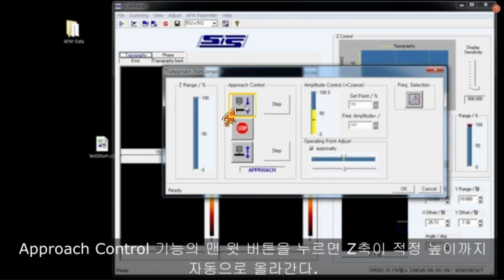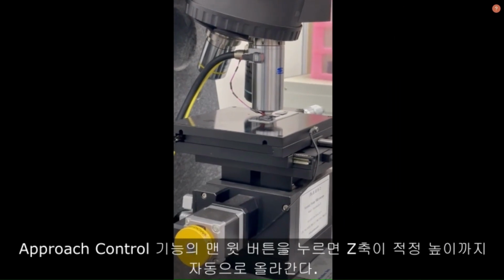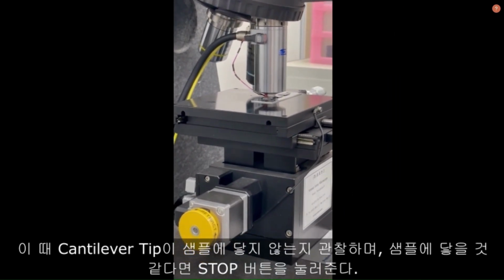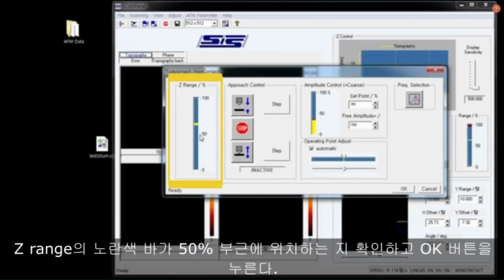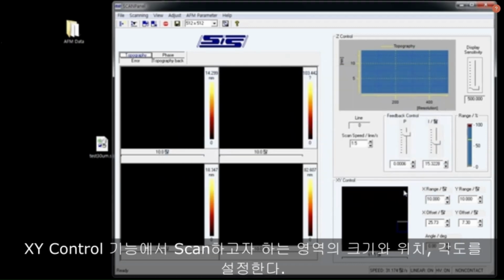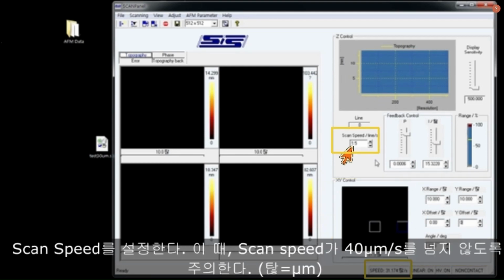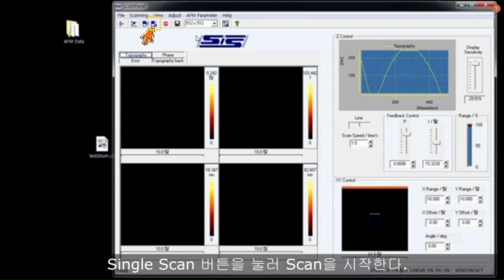Then click the upper button of the Approach Control section and see the equipment approach the cantilever tip and stop automatically. Click the OK button if you can see the Z-range bar located near 50% and turned yellow. Set the scan size, offset, and angle in the XY control section. Also set the scan speed. The total scan speed must be less than 40 micrometers per second. Click the single scan button.